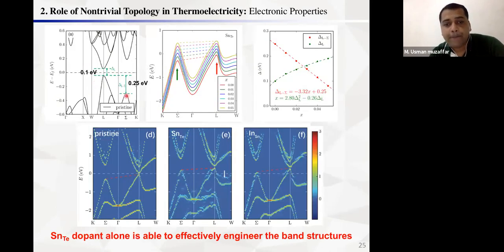So this is the band structure of the SnTe system in the pure band structure. You can see it has a fundamental band gap with the value of 0.1 eV, and as I mentioned previously, this one has two subvalence bands. At the L point, it has a light hole band, and at the sigma, it has a heavy hole band. So between these two bands, there is a large band gap. So we need to do the doping so that we can reduce the energy gap between these two bands.